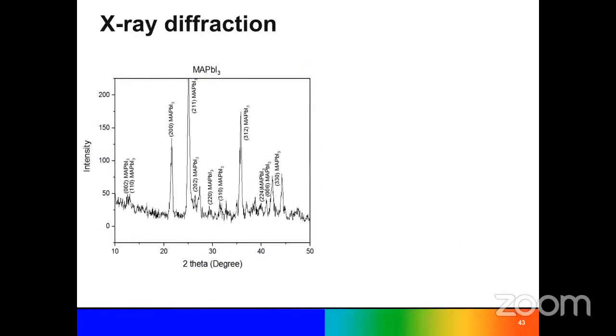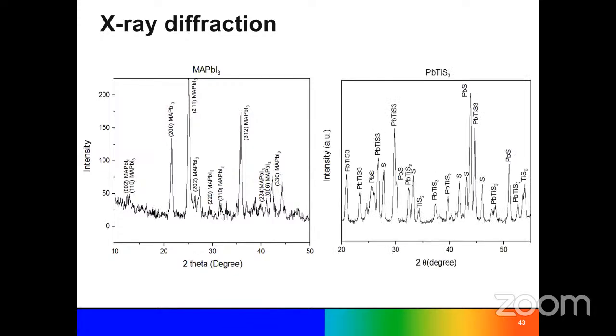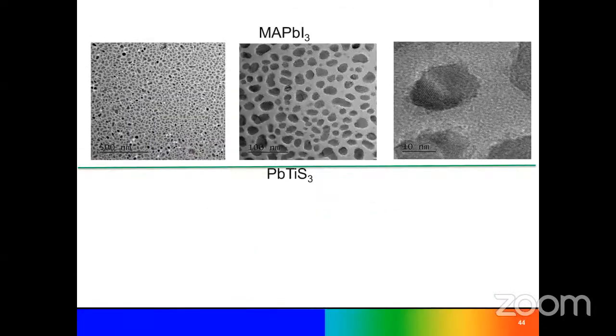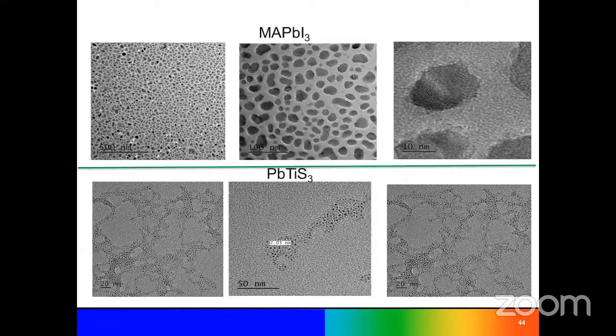So here, first, after fabrication of the perovskite materials, we check the XRD property to see whether the proper phase formation happened or whether there are any impurities. All those things we have checked. Then we also check the size of the materials, and we tune the size by changing the temperature or other parameters.